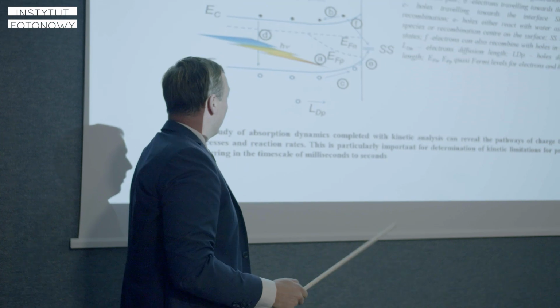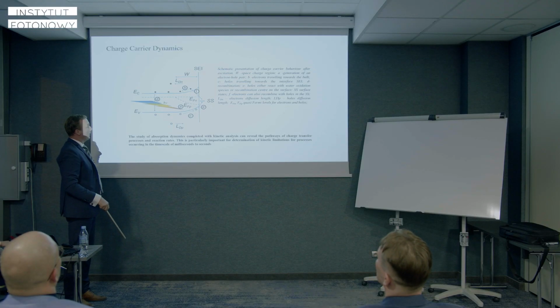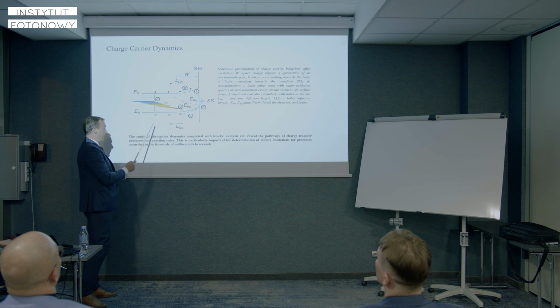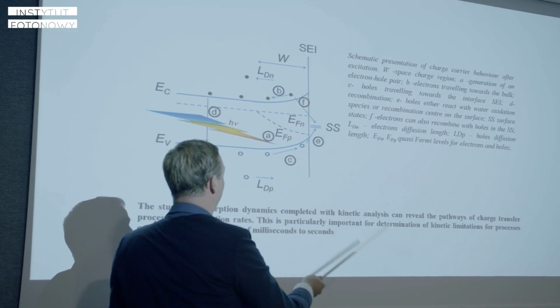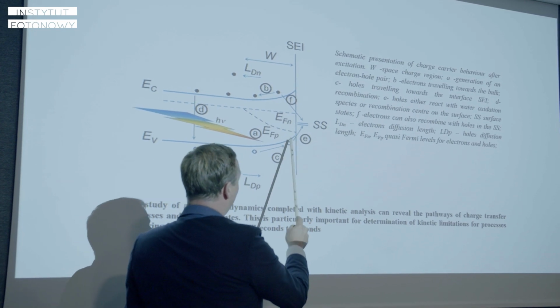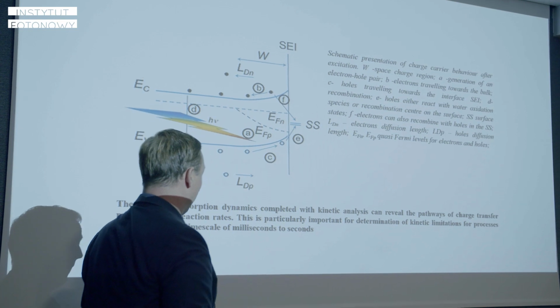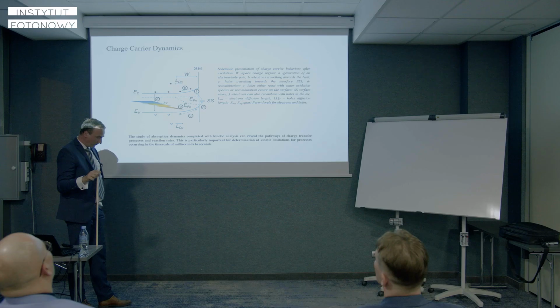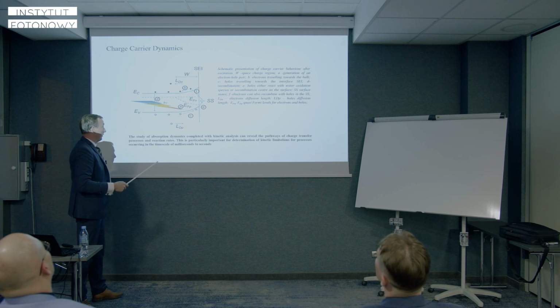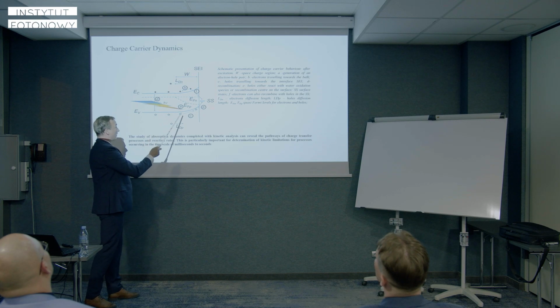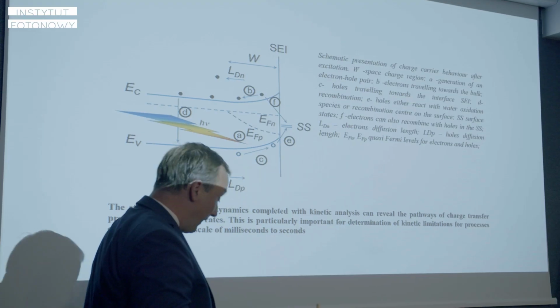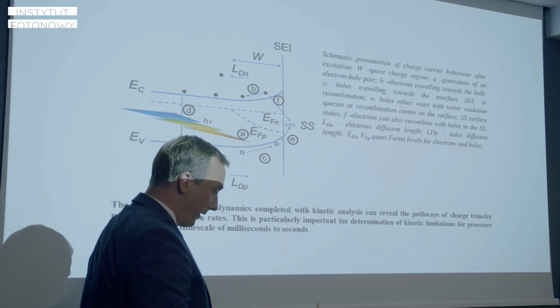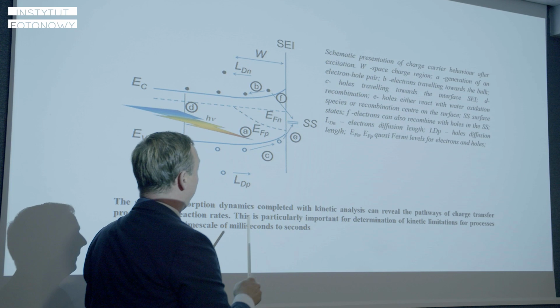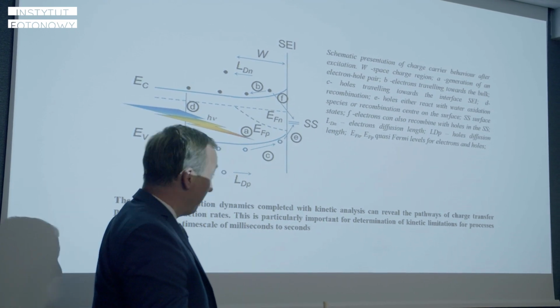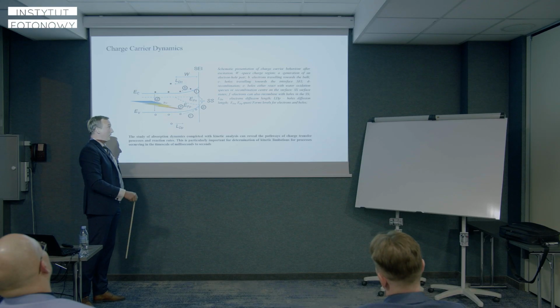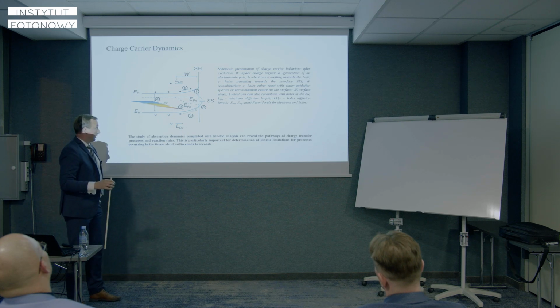Okay, so nevertheless, when the photon is absorbed by a semiconductor, it can generate a hole and electron, and if we are lucky and the depletion layer is big enough and we have an electric field which allows the hole to go to the surface, we can have a photooxidation process at the surface. Alternatively, the electron and hole can recombine in the bulk of the semiconductor. Also, they can recombine on the defects of the structure on the surface, and there is also a problem because sometimes holes and electrons can react with the semiconductor. But finally, if none of these things happen, we can have an oxidation process at the surface of the semiconductor.